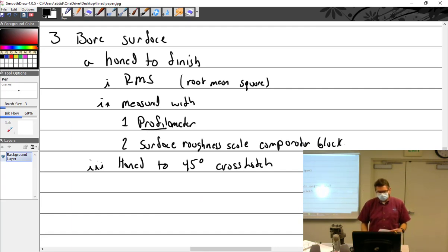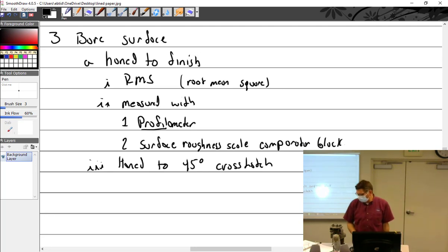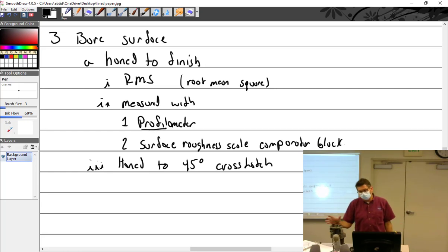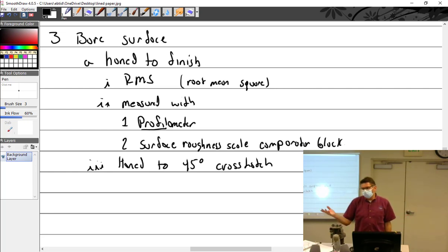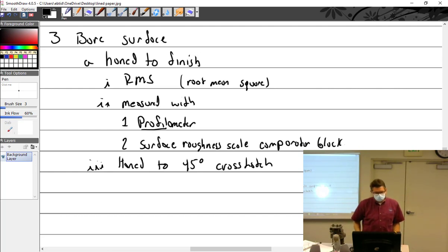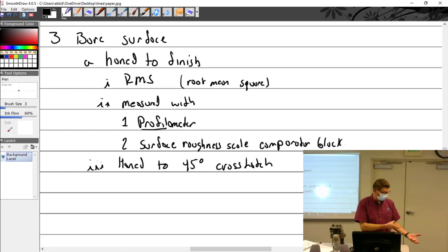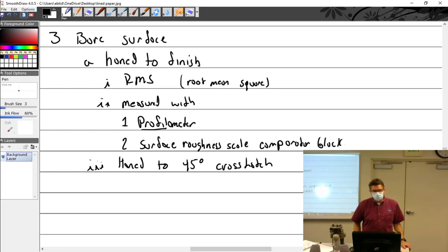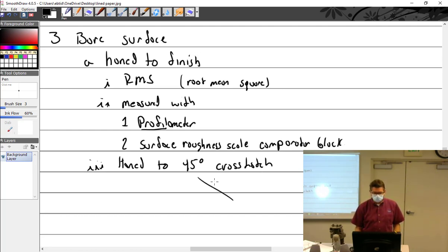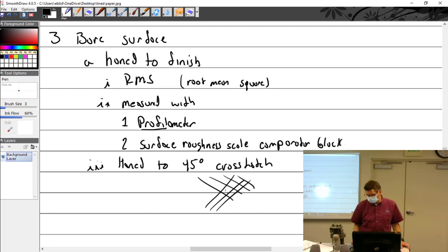This one's going to follow all the imperfections. The bottle brush even more so. Whatever imperfections you have out of round, it's just going to accentuate it. But the one I had, we would actually do like a four swipe with it and then take it off and evaluate. You could just see all the high spots, low spots, where the rings have been sitting, where they weren't sitting.